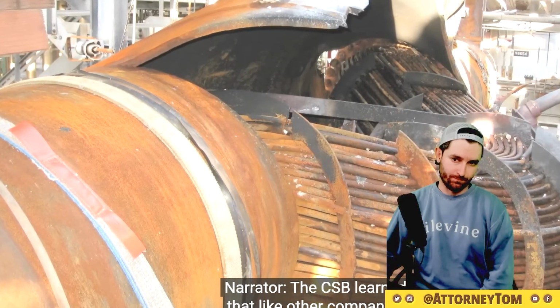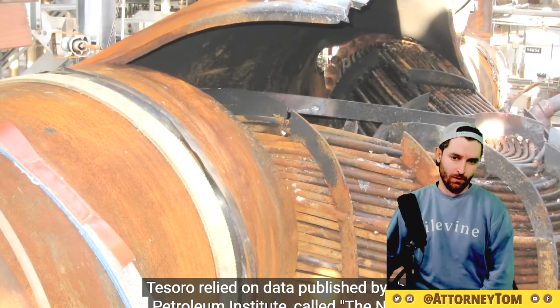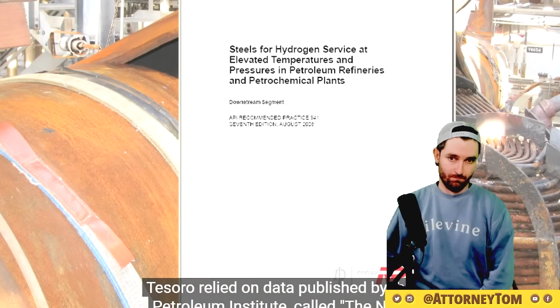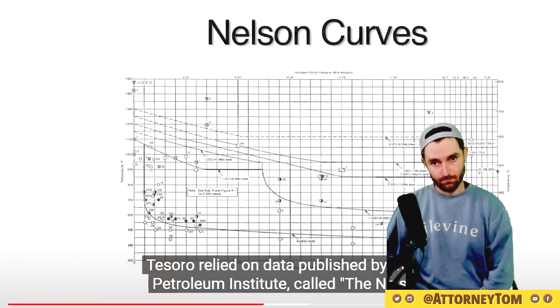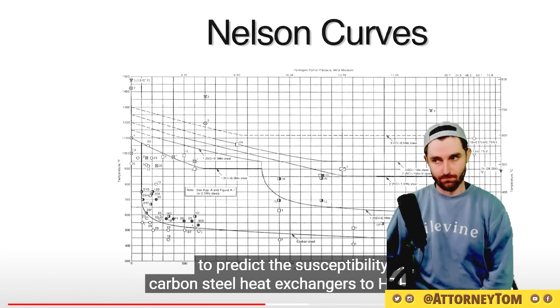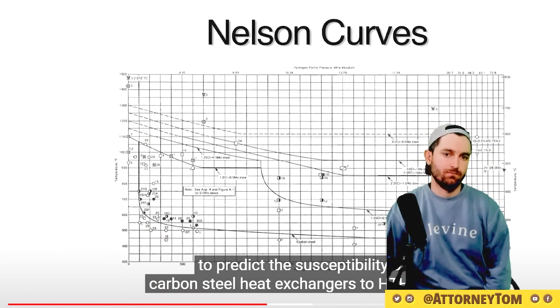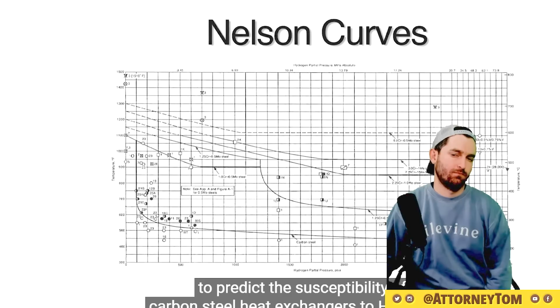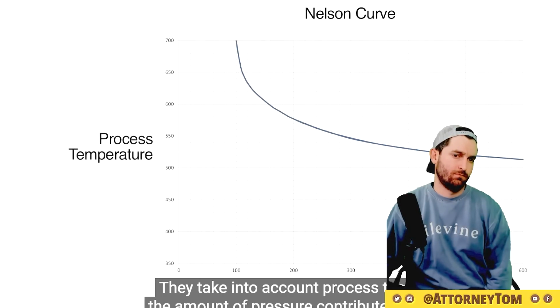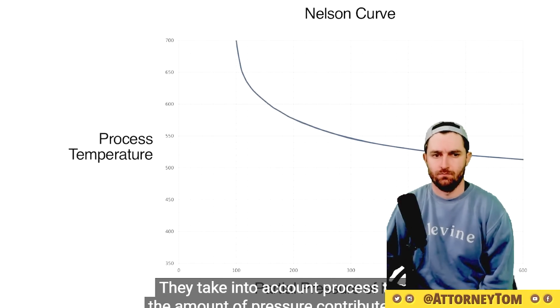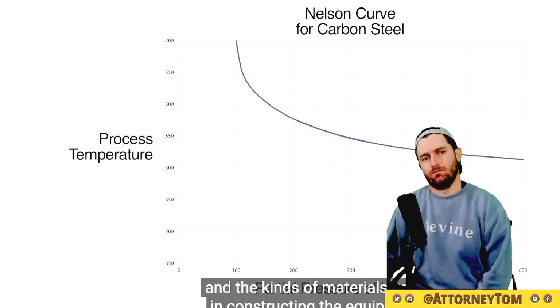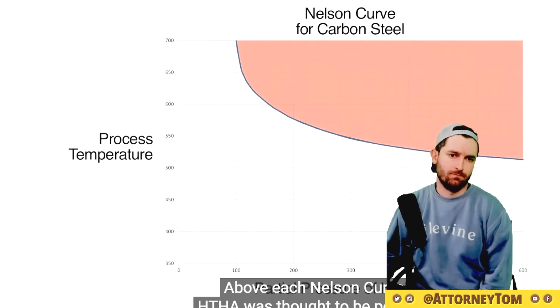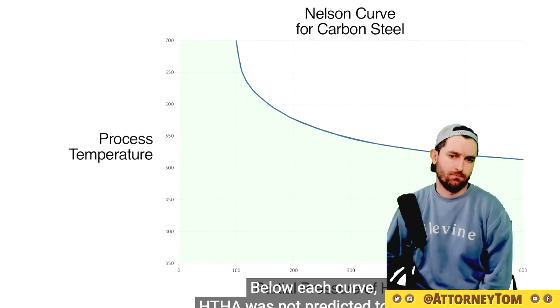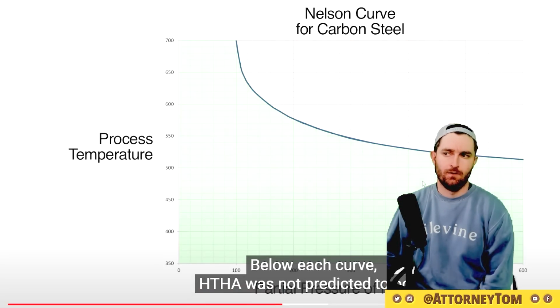The CSB learned that, like other companies, Tesoro relied on data published by the American Petroleum Institute called the Nelson Curves to predict the susceptibility of the carbon steel heat exchangers to HTHA damage. They take into account process temperature, the amount of pressure contributed by hydrogen, and the kinds of materials used in constructing the equipment. Above each Nelson curve, HTHA was thought to be possible. Below each curve, HTHA was not predicted to occur.